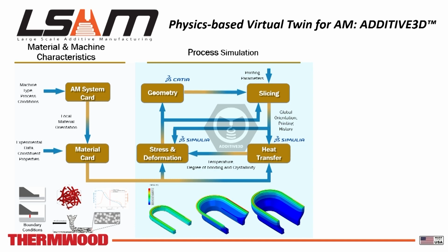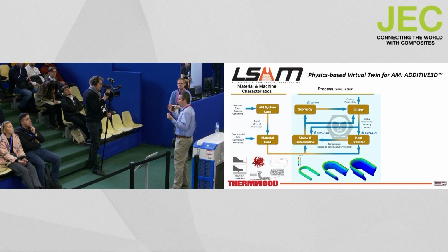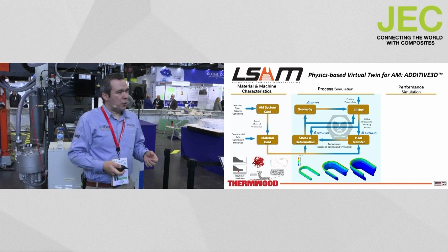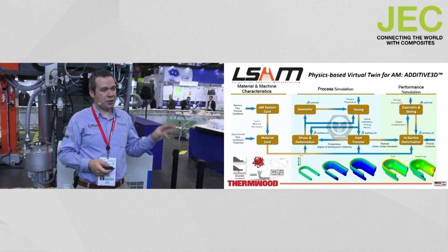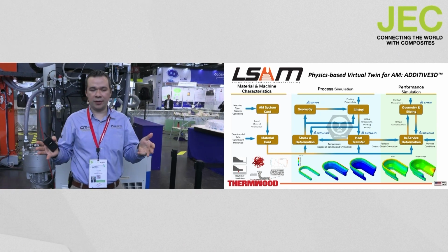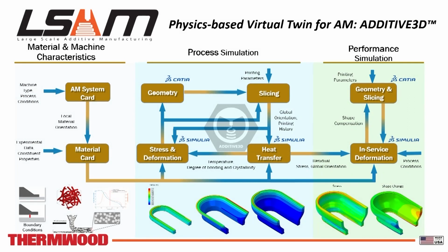It's a transient simulation. We basically carry out a sequentially coupled thermomechanical analysis that allows us to predict temperature, crystallinity, interlayer bonding, residual stresses, deformation, and be able to iterate virtually and avoid expensive print trials that might result in a print failure. But then we can take the information of the as-manufactured shape and investigate its performance characteristics. Performance clearly depends on the context where the printed part is going to be used. If it's a mold, like in this example, there is an isotropic shape change that occurs as the mold goes in the autoclave. So we can predict and compensate for that, so that we machine a compensated shape that is going to develop the right shape when it goes in the autoclave.